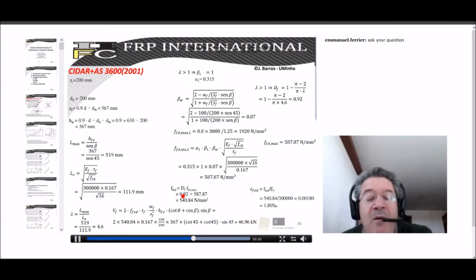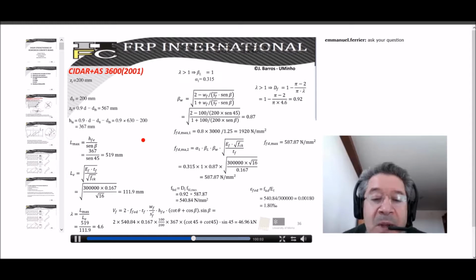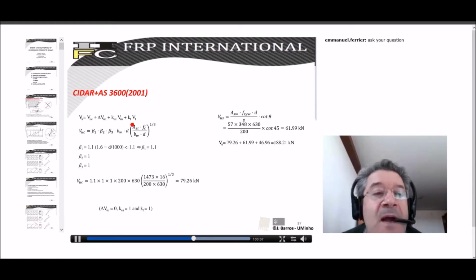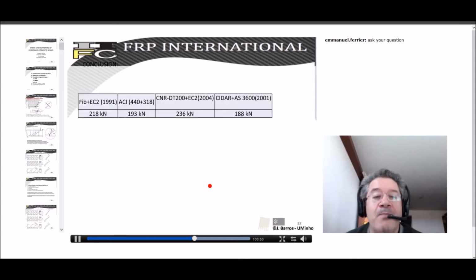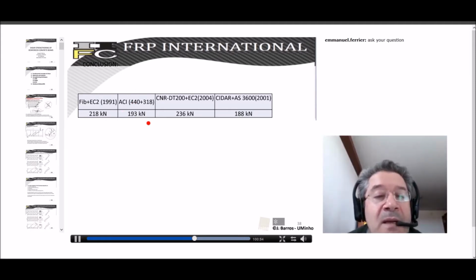So now we use this term here, we replace, and consequently we obtain the contribution of the FRP. Comparing, according to the CIDAR, and considering the Australian design guideline to evaluate the contribution of the steel stirrups and the concrete, so this is the equation to evaluate the contribution of the concrete, while this is the equation to estimate the contribution of steel stirrups. And finally, we obtain the shear capacity of the beam, that is the contribution of the concrete, the contribution of the steel stirrups, and the contribution of the CFRP system. And we can compare in this table.